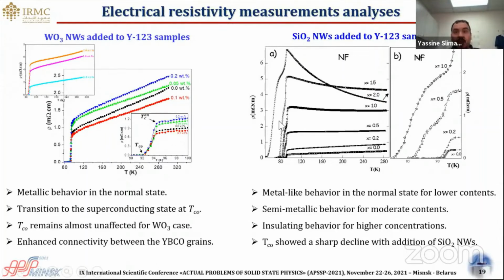Considering the case of adding insulating nanomaterials like silica oxide, we observed metallic-like behavior in the normal state for lower contents, semi-metallic behavior for moderate contents, and notable insulating behavior for higher concentration. This can be understood due to the nature of the inclusion. Evidently, the critical transition temperature showed a sharp decline for higher concentration.